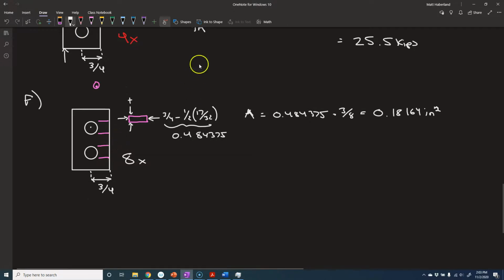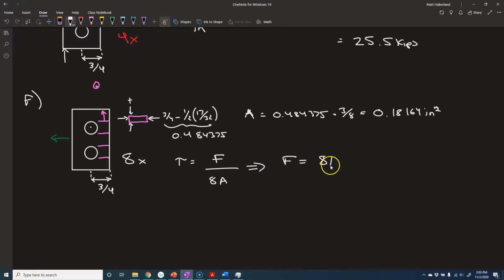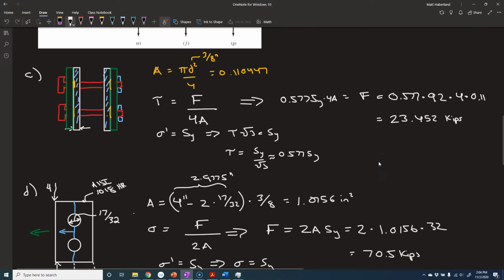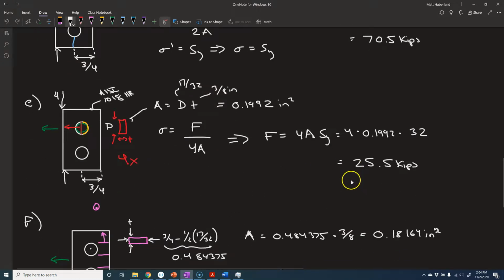Now, why do I say shear? Because these areas that we're talking about, their normal is in this direction, that's perpendicular to the applied load. So we're analyzing them in shear. The shear stress in them is the force divided by 8 times the area that we have. Now, according to von Mises' criterion, we fail when the force applied is 8 times the area times 0.577. For the same reason, the yield strength in shear is 0.577 times SY.